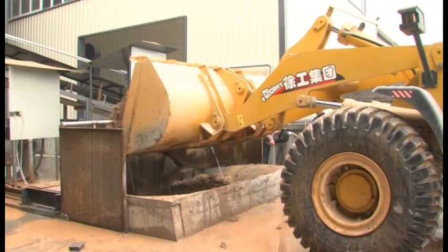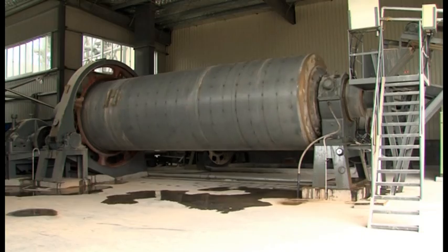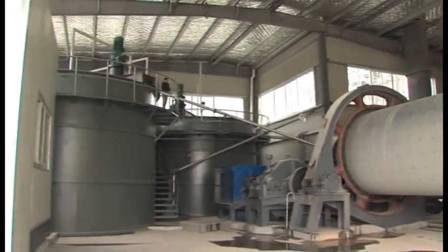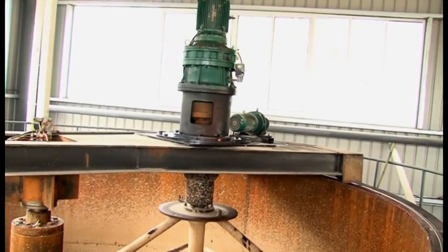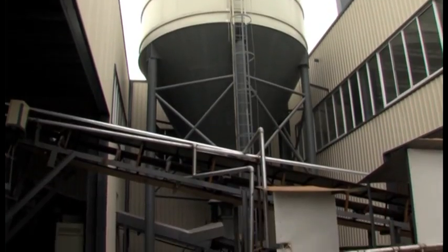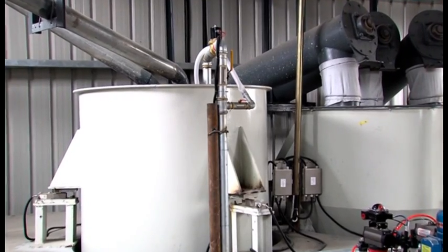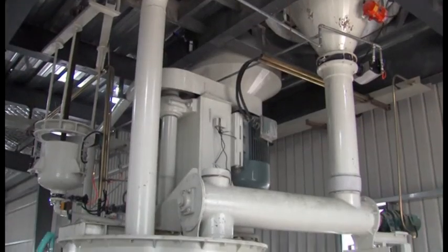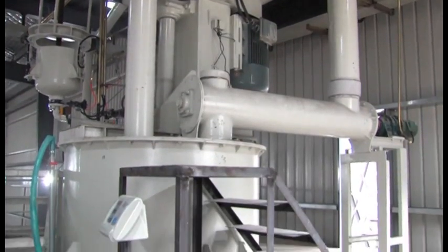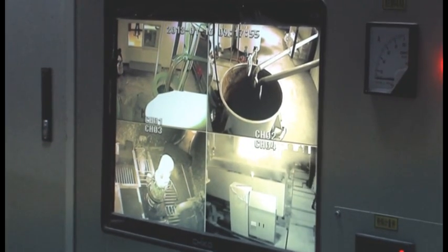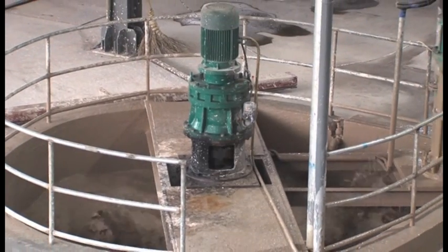At first, fly ash or sand are ground through a ball mill and made into slurry stored in the slurry tank. The cement and quicklime are transported into the silo for storage. The prepared raw materials are measured through an electronic powder scale and an electronic slurry scale, and then transported to the pouring mixer for high-speed mixing. The measurement is controlled by PLC.